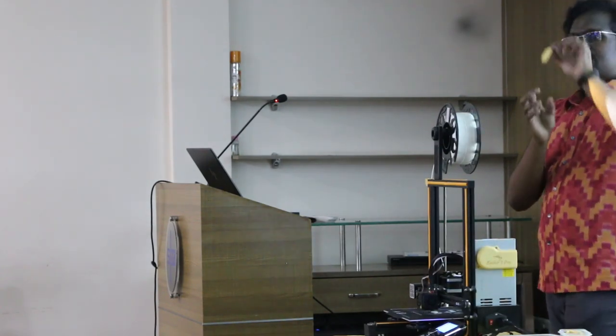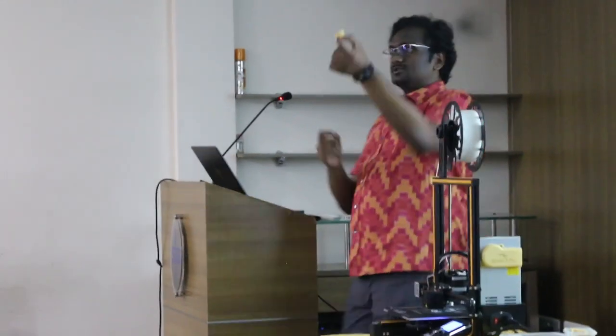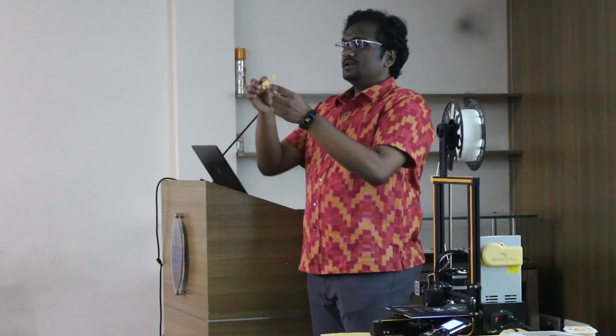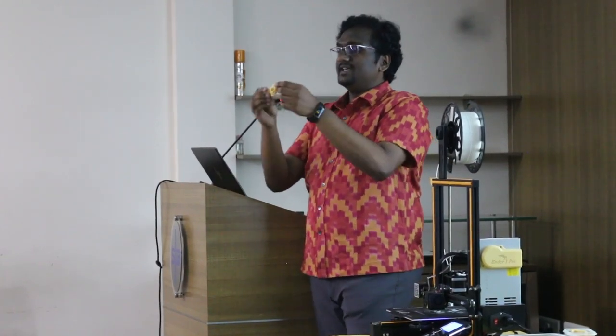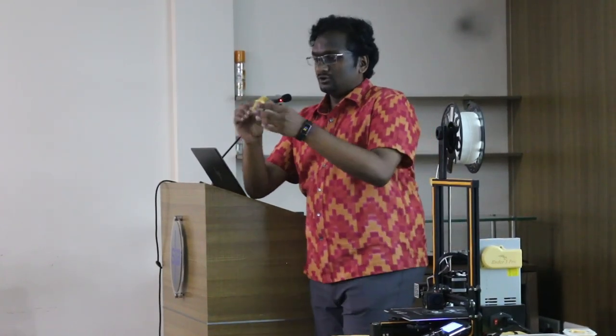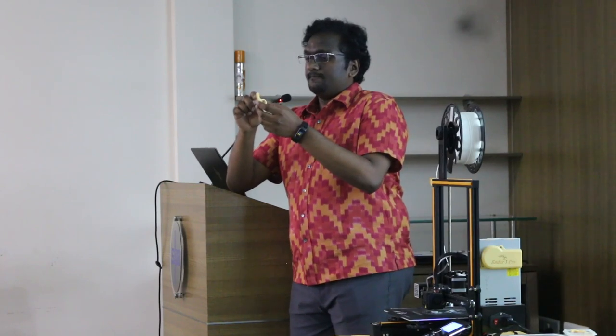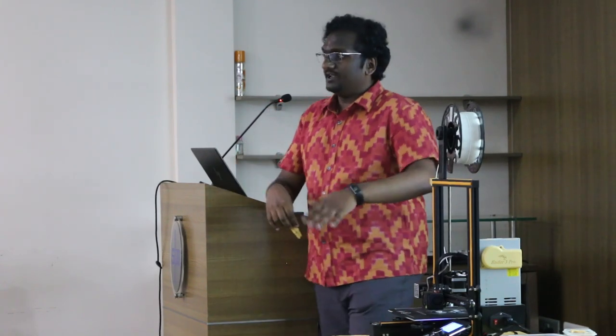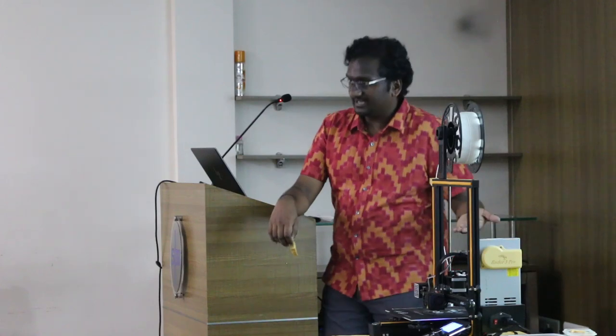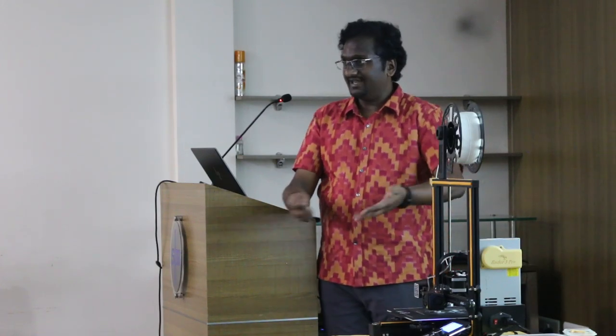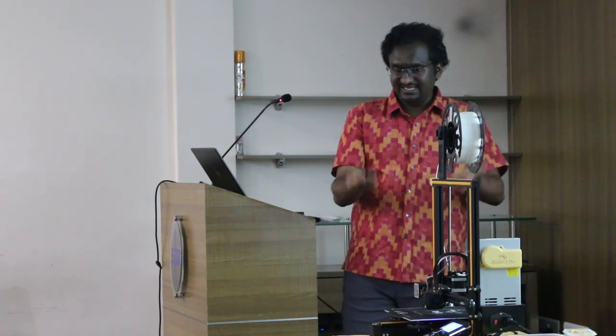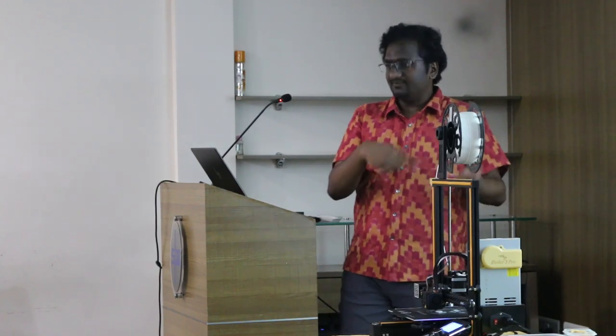You get a mess like this. What had happened was it started printing this layer, and I intentionally made this fail, just to show this. I reduced the bed temperature. What is the bed temperature? This is the bed. The one it's printing on is the bed, and that actually heats up. It has a heating element on it, so the entire thing is heated to 60 degrees Celsius. There's a feedback system which keeps it there.